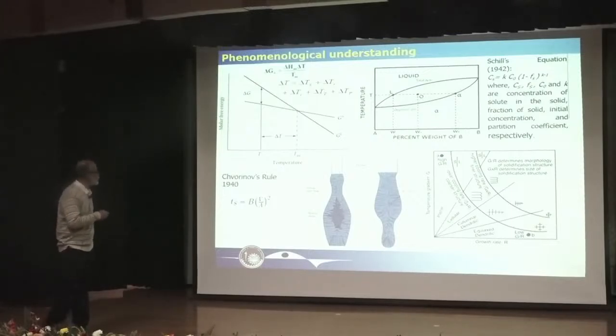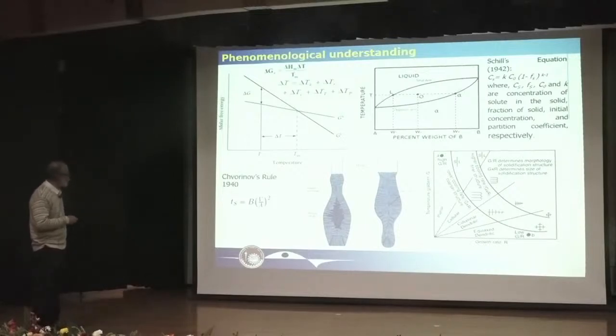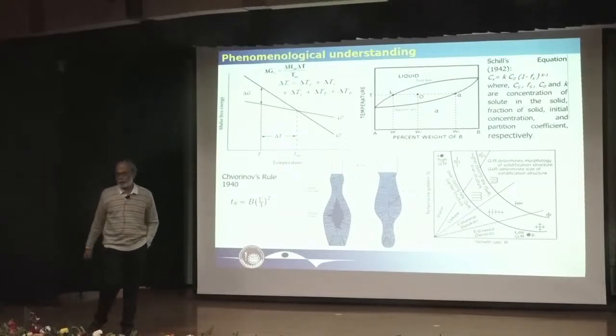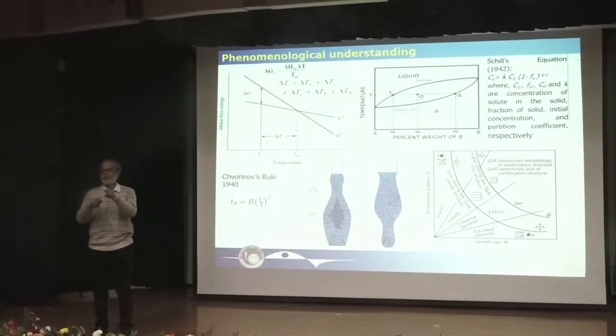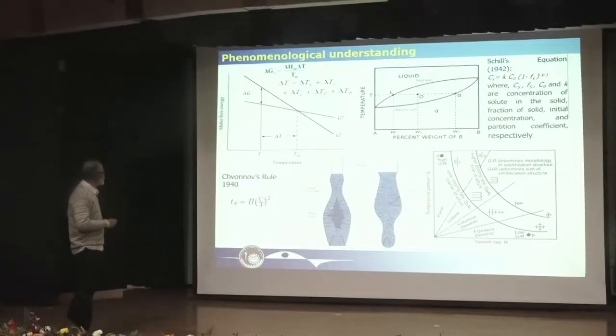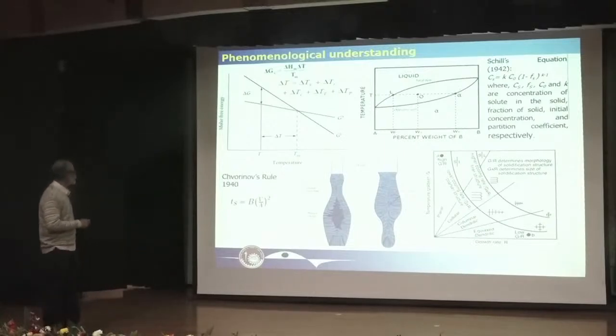So different parameters contribute to the undercooling, and by virtue of that, some driving force was achievable. Because at equilibrium, nothing transforms. When delta G between two phases is 0, it doesn't transform. Something has to happen so that the energy reduces. And this difference is the driving force for solidification. So this was basically a parameter which was correlated with the non-equilibrium feature of the process.